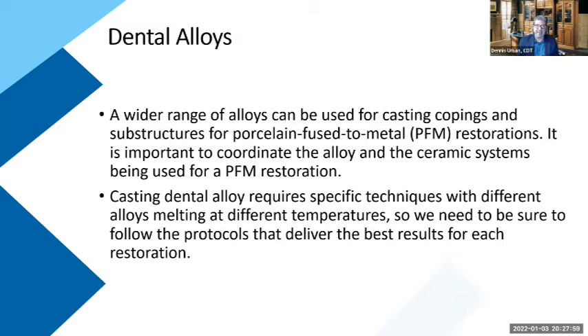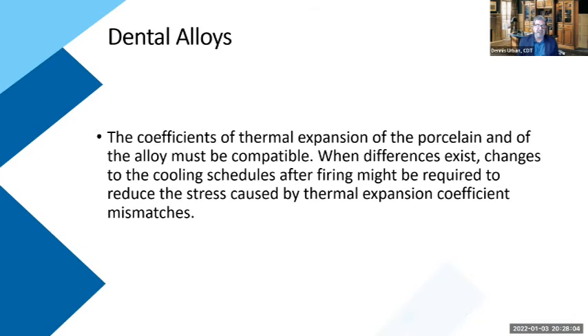And that was back in the days where a lot of gold and a lot of semi-precious metal was being sold. The coefficients of thermal expansion of the porcelain and the alloy had to be compatible, and we saw a lot with different alloys, especially with silver. We used to get a lot of greening, which was from the high silver content in the alloys. Sometimes we got too much oxidation and the porcelain would chip off, or the bonding wasn't that great. So when those differences exist, changes to the cooling schedule of the firing might be required to reduce the stress caused by thermal expansion coefficient mismatches.